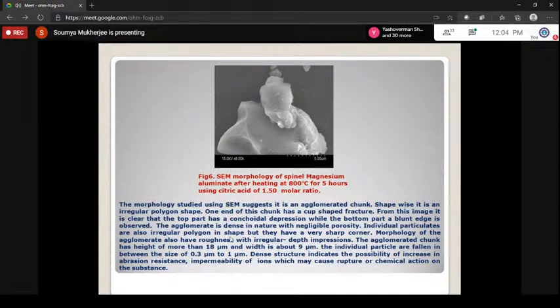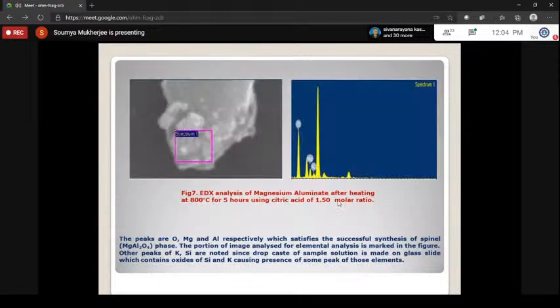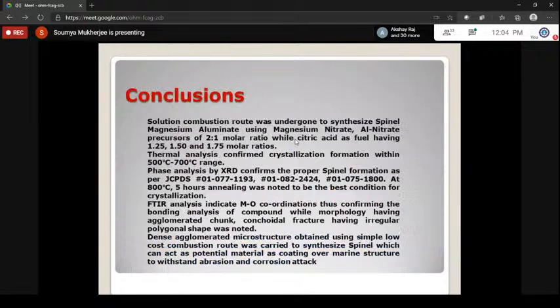From the microstructure, we are getting the individual particles to be in the range of some micrometers, that is 0.3 micrometer to highest 1 micrometer. Now, this is the EDAX analysis, from where we are getting the magnesium, oxygen, aluminum presence, and it supports our FTIR analysis. So in a very short time, we have synthesized the spinel compounds in a very simple chemistry route,